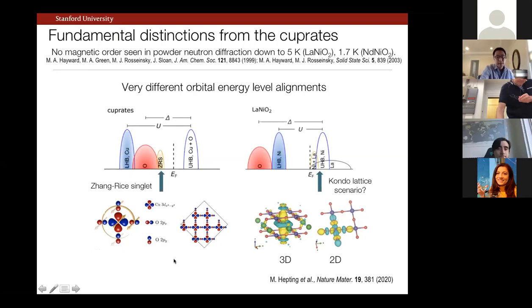Okay. So how about the case for the nickelates? The nickelates, again, by virtue of where we are electronically, have a kind of similar overall landscape. But the caveat is that when we start to dope the system or play with the system, we're living very, very far up compared to the edge of the oxygen 2p band. Namely, we're looking at a manifold of states composed of hybridization between the upper Hubbard band of the nickel 3d states and actually the 5d electrons of the lanthanum, neodymium. The details don't really matter here, with a broader bandwidth across here.